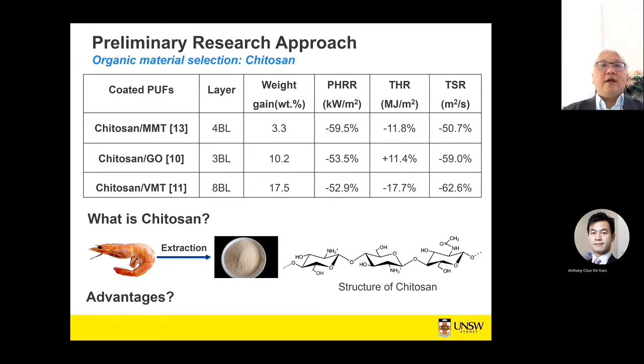So what this table tries to demonstrate is that with the introduction of chitosan and MMT, the weight gain is only 3.3%, but the peak heat release rate reduction and the smoke release rate reduction are actually quite significant. So this gives us the idea that there is a possibility to use chitosan as the cross-linker to bind the 2D nanosheets based on MXene.